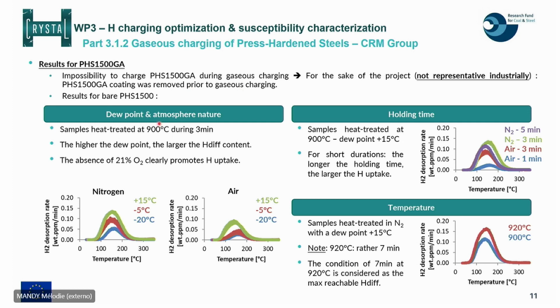What you see is that the conclusions that we have seen for Usibor 2000 are quite the same for these bare materials. So you see that we have a strong impact of the atmosphere. In nitrogen atmosphere, we have a larger uptake than in air. We have also this effect of the dew point, which is well marked. And the effect of the holding time and the temperature are maybe a bit less marked, a bit less significant than for PHS 1500, but remains less important than the atmosphere effect.